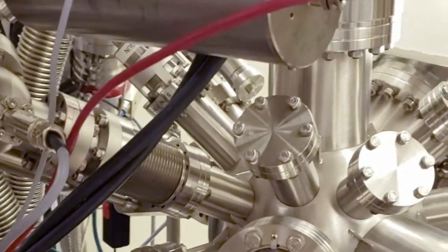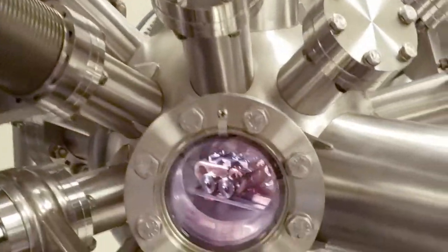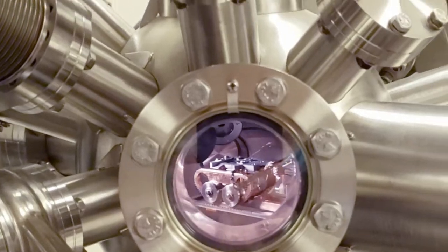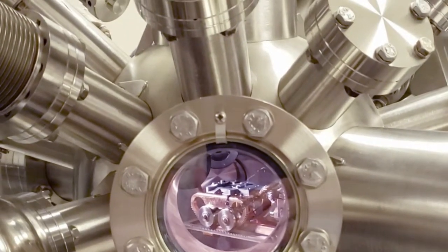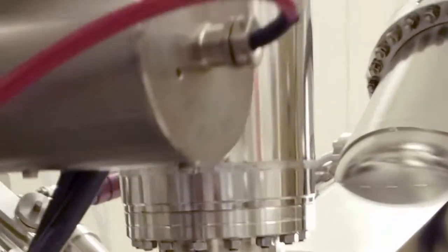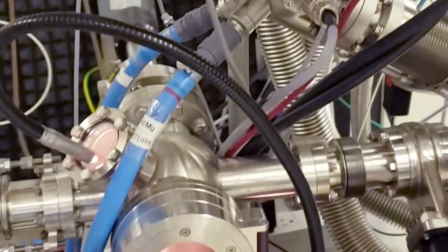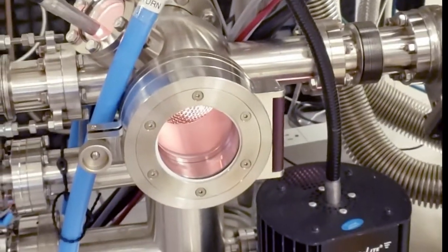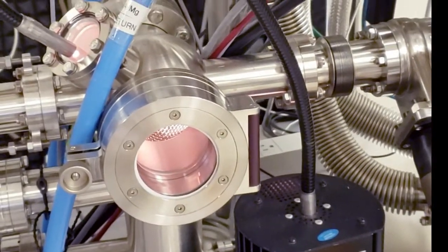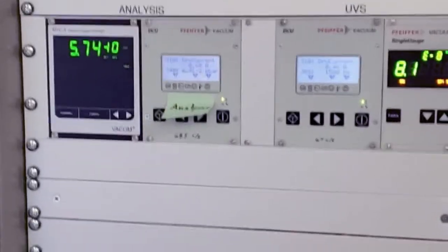The X-rays from the source irradiate the sample, and the sample is located inside the analysis chamber. The electrons that are emitted are analyzed through a hemispherical analyzer and then detected. Samples are loaded in an air interlock as shown here. Our pressure in the instrument is typically in the low 10 to the minus 10 millibar range.